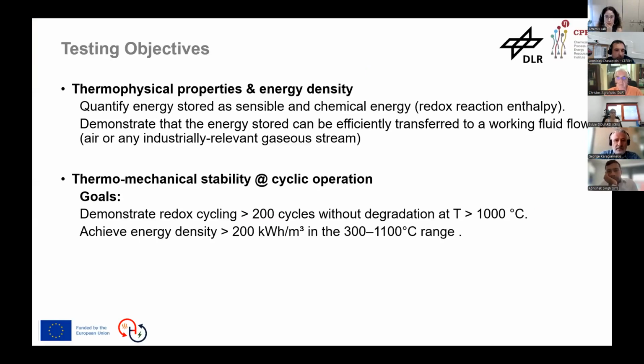Okay, our primary objective is to quantify how much energy can be stored using both sensible and chemical means, particularly through redox reactions. We are also focused on confirming that the stored energy can be effectively transferred to a working fluid such as air. Another goal is to validate the thermal and chemical stability of these materials and final structures under cyclic conditions, specifically over 200 cycles at temperatures exceeding 1000 degrees Celsius. And finally, we aim to achieve an energy density of greater than 200 kilowatt hours per cubic meter in the 300 to 1100 degrees Celsius range.